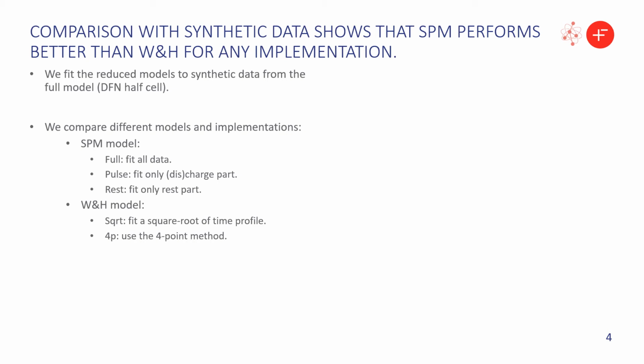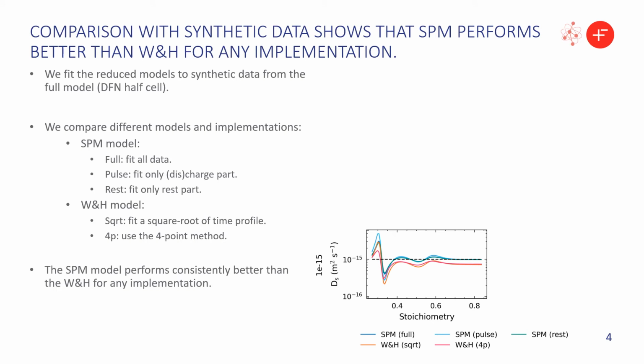So we can just fit a square root of time profile, taking all those points in that transient, or we can use this 4-point method, which is presented in the Weppner and Huggins paper, which takes only 4 points at the beginning and at the end of the pulse, and estimates it. And what we see when we compare here, basically we compare all of them, and the dashed line represents the actual or the true diffusion coefficient for the synthetic data. And what we can see is that no matter the implementation, the SPM performs better than the Weppner and Huggins model.